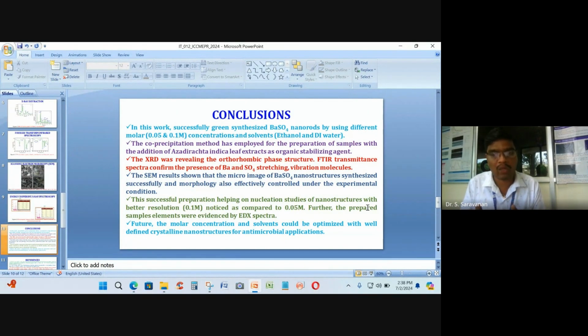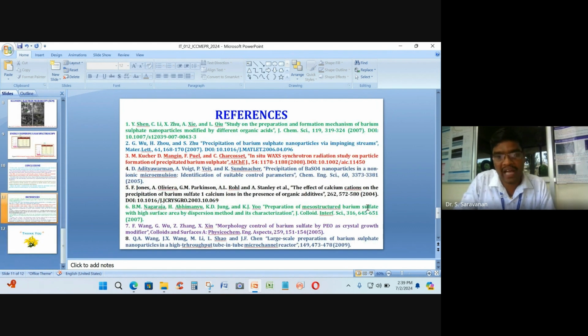sulfate group molecules are present in the transmittance spectra. Again, the same result shows that nanostructures are present, which look like nanorod structures, and the morphology is improved from ethanol to DI water-based barium sulfate. So this successful preparation of nanostructures we got from 0.1 molarity barium sulfate, and the EDX spectra also confirmed the elements present. In future, these molar concentrations and solvents would be optimized for well-defined nanostructures for antimicrobial applications. So these are the references that I have used.